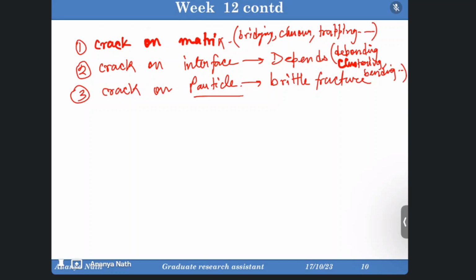Then if the particles are getting fractured, meaning if there is some crack, the particles may get fractured, and due to that the number of particles will increase. If the fractured particles are still bonded with the matrix, then the number of interfaces has increased, and due to which the number of crack initiation sites is increased. So there will be an effect of the crack initiation sites, and there will be an effect on the strength or ductility as well.